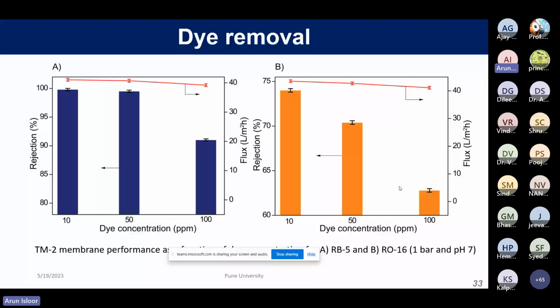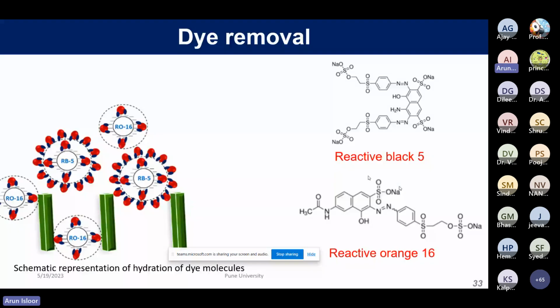And then again, the dyes RB5 as well as RO16 were tested. So here you can see the removal of RO16 came to around 74%, whereas for RB5 it is almost 99%. Again, because of the size exclusion, the RB5 molecule is much larger than the RO16 type of dye molecule. RO16 can pass through this one. So a higher rejection percentage was observed for RB5 than for RO16. You can see the structures also, which are given here.